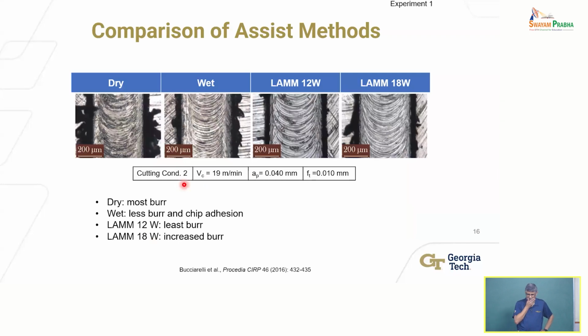So what does it look like in terms of the geometries that are produced? This is looking under an optical microscope at dry versus wet. Wet would be the submerged case that you saw in the video, versus using the laser assist with 12 watt laser power or 18 watt laser power. You can see here, there are burrs that do form. This dark region, this black region, are basically burrs that form on the side. With lasers, you still see some burrs. The least burr for the laser-assisted case is for 12 watts: less energy, and therefore less softening, and therefore less plastic flow of material. So this is what happens, increased burr.